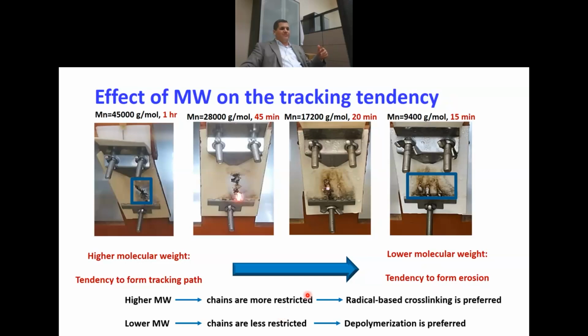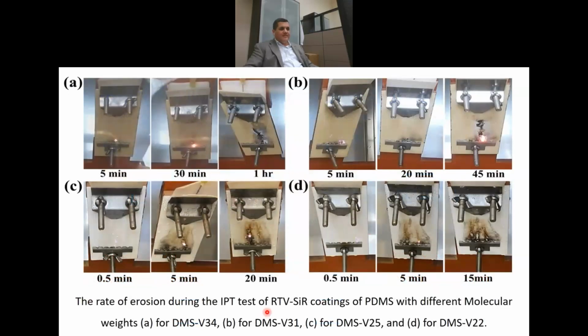So the chain motion is more restricted, sorry, in case of the long chain, not in the short chain ones. This is just to show you what happened exactly with time, because we do the test, we apply the 4.5 kilovolt, and we see how much the sample will handle until it makes a big failure like this in this case. So up to what limit the sample can handle, and this shows you very much the trend of all. There is a variation of the IPT behavior versus the molecular weight effect.